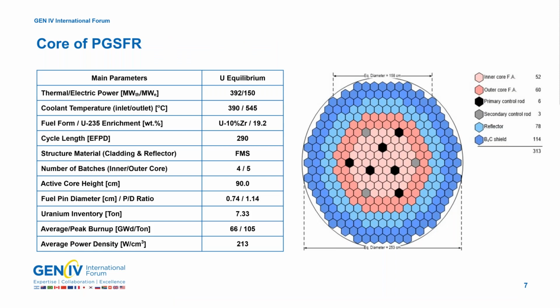This shows the core design of the reactors. Its thermal power is about 392, and the inlet temperature is about 390 also. And the fuel used is LEU fuel, about 19.2. It can reach a cycle length of about 290. And the cladding is ferritic martensitic steel, which has a very low swelling rate. And the core height is about 90 centimeters, and the pin diameter is about 7.4 millimeters.